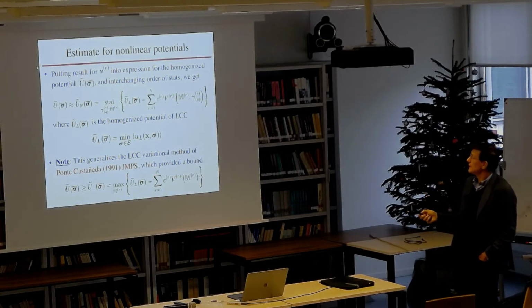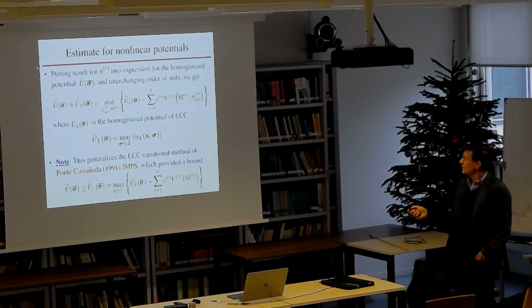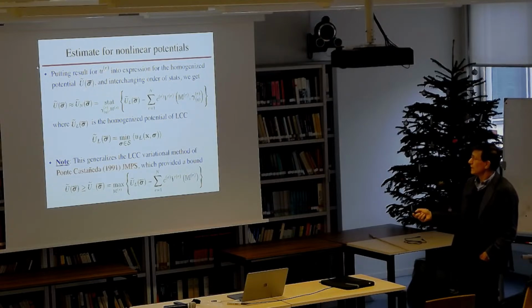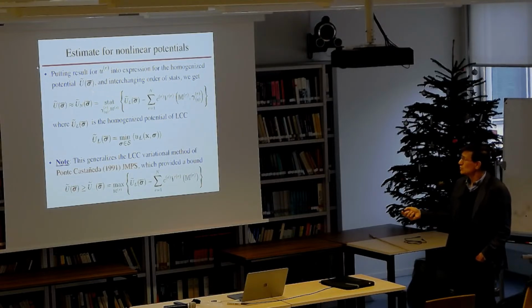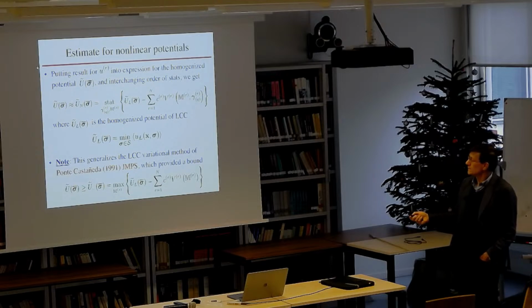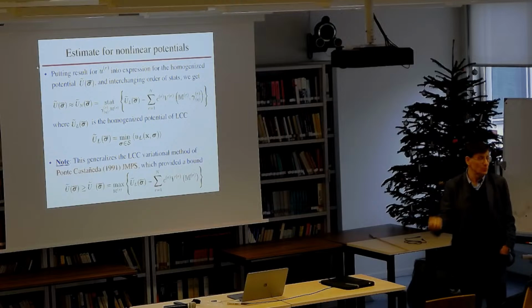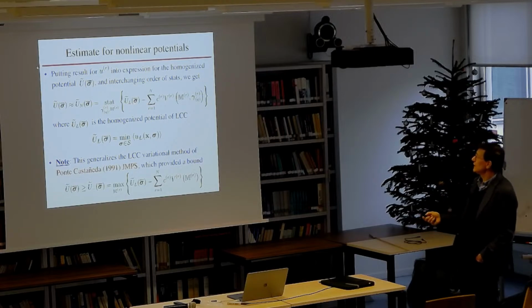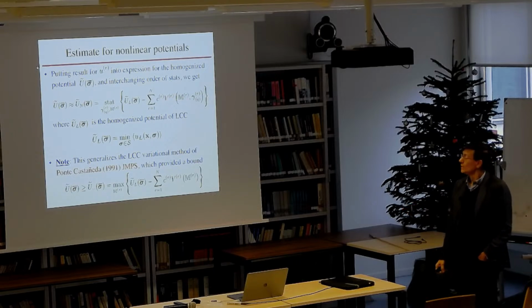In any case, if you make use of those results for the stress potentials of the phases, you could get a corresponding result for the effective potential of the composite. And it's not an exact result. It's an estimate. It's a variational estimate that looks like this, right? The effective potential of the linear comparison medium, which we know how to generate, right? We know how to do. And this combination of things that depend on the nonlinearity of the phases.